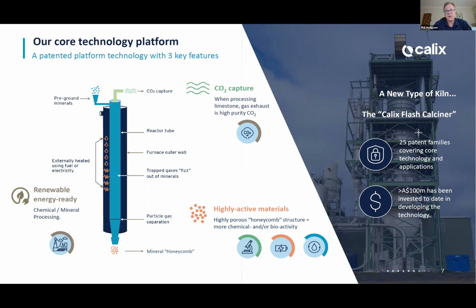The second advantage of our technology is we're not contacting any furnace gases with the particles, so they can stay nice and pure. We can actually maximize what's called the surface area or porosity of these particles. As any trapped gases in those tiny particles come out, it creates a tiny pore or channel. Because we're only heating for a very short period of time, just 10 or 20 seconds in the kiln, those trapped gases can come out and create a very highly porous structure, not contaminated with furnace gases. And so we can make high surface area, quite pure materials. We're developing that aspect of the technology into business streams in wastewater treatment, in advanced batteries, in biotech applications as well.